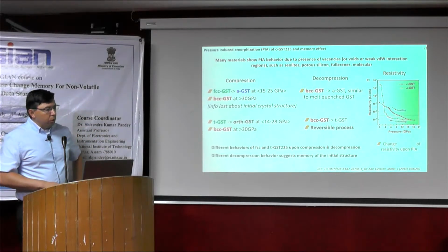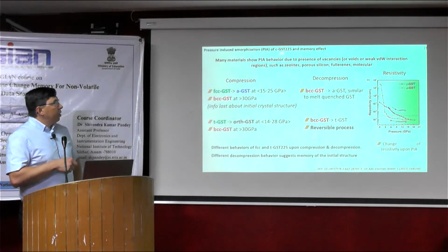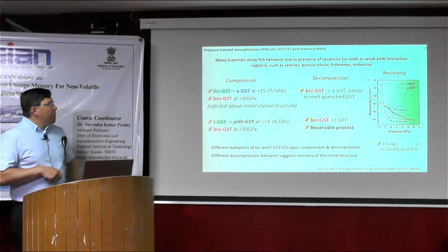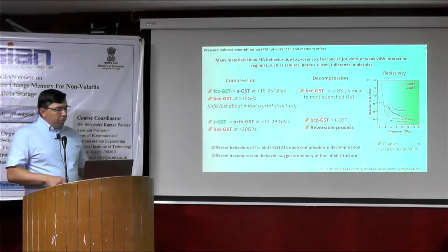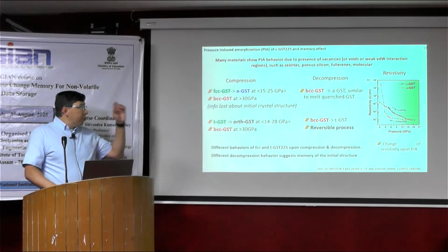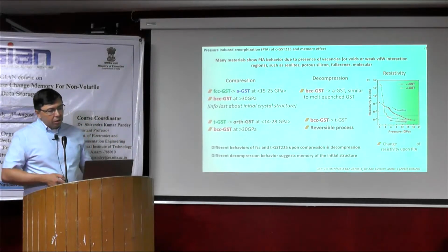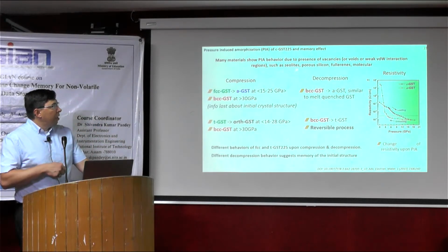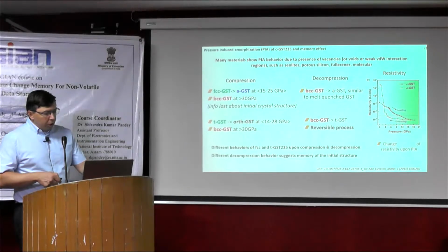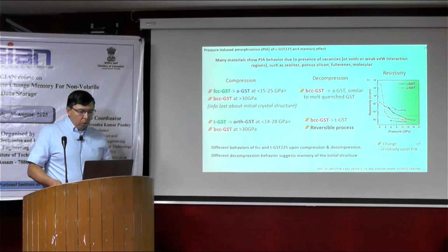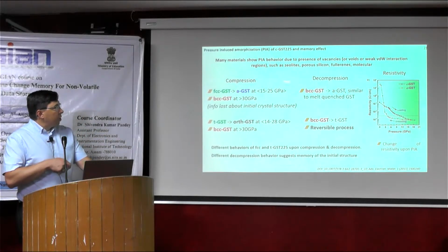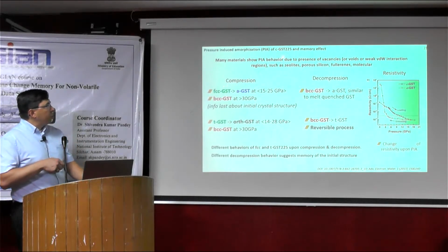Now let us look at the pressure-induced amorphization of cubic GST and the memory effect. Many materials possess this behavior due to the presence of vacancies, voids, or weak van der Waals interactions, like zeolites, porous silicon, fullerenes, molecular crystals. And let us look at our system, the GST on compression and decompression. This is crystalline GST 225. So we consider two phases, cubic phase FCC GST and TGST.